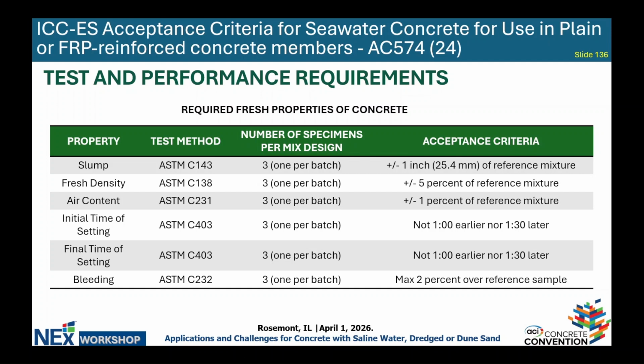So for slump, it's within 1 inch of the reference mixture. For fresh density, within 5% of the reference mixture. For air content, within 1% of the reference mixture. For time of setting, not 1 hour earlier or not 1 hour, 30 minutes later. And then bleeding is max 2% over the reference sample.